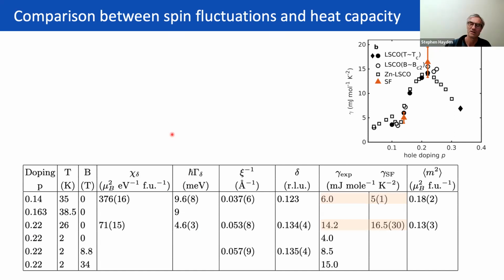That's right. I'm a bit uncomfortable with the total magnetic scattering. What we found is that there's a piece of scattering, as it were, at low energies. It's on the tail of something else. Obviously, there's a sum rule, and there's other incoherent stuff in other places in reciprocal space and energies. But these coherent fluctuations that are giving these 4 peaks, they've got weaker, but they've gone down to lower energies.